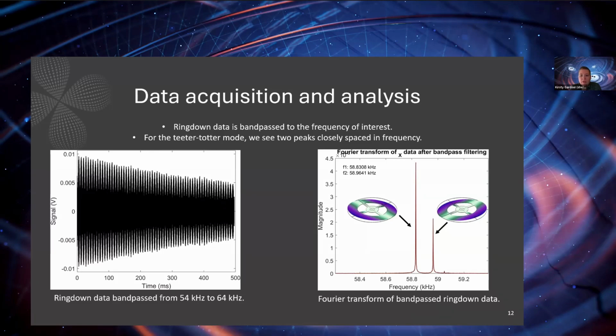In a symmetric microdisk, there are two orthogonal modes that are degenerate. Because of the fabrication imperfections, a microdisk is very rarely perfectly symmetric, so that degeneracy is broken. And so instead of a single frequency, we see two very closely spaced frequencies. The graph on the right-hand side is the Fourier transform of the data on the left so that we can see what it looks like in frequency space. And you can see those two closely spaced frequencies, which is what leads to the beat frequency in the ring down on the left-hand side.